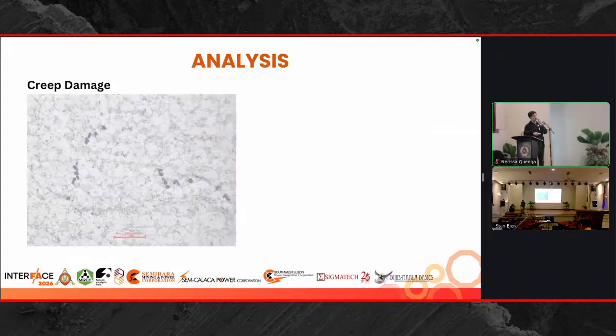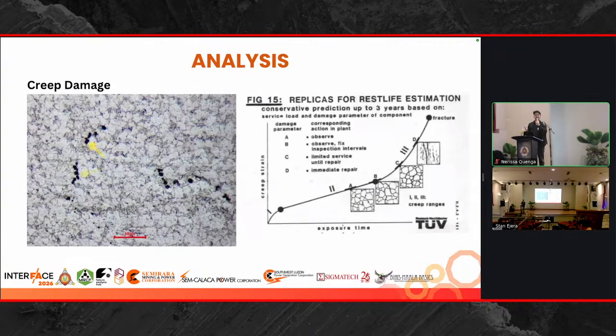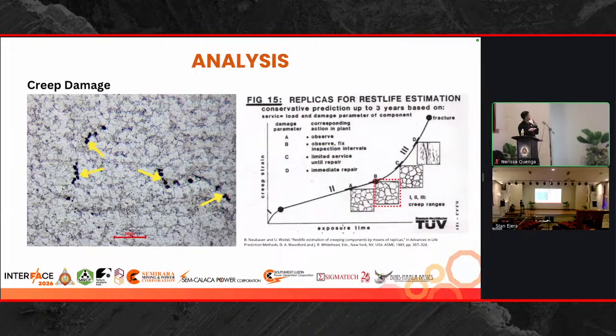So first, one of the features that we are mainly looking at in high energy material components is creep damage. So creep damage is a temperature and time dependent failure. So eventually, a boiler tube in service for a very long time will pose deformation, and this deformation is manifested on the microstructure by cracks. So this figure is an example of a micrograph that we have taken from one of our lab testing. As you can see here, there are voids, creep voids, as we can call it, and they are starting to orient to form a crack.